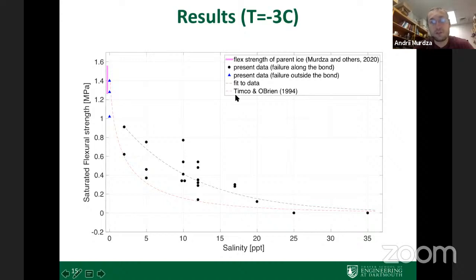And for comparison, we provide data from Timco and O'Brien, where they summarized over 2,000 tests. And interestingly, the trend is very similar. The only thing is that our data are slightly higher. We have a greater flexural strength. And I explained earlier that it's probably because of the grain size difference.